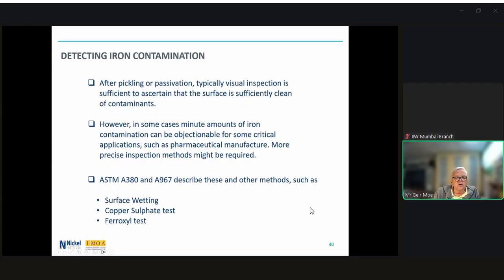And so even though we've talked about passivation and how to remove iron contamination, after pickling or passivation, typically visual inspection is sufficient to ascertain that the surface is sufficiently clean of contaminants. However, in some cases, minute amounts of iron contamination can be objectionable for some critical applications, such as pharmaceutical manufacture. More precise inspection methods might be required. ASTM A380 and ASTM A967 describe these methods for detecting iron contamination, and the three primary methods are surface wetting, copper sulfate test, or ferroxyl test.